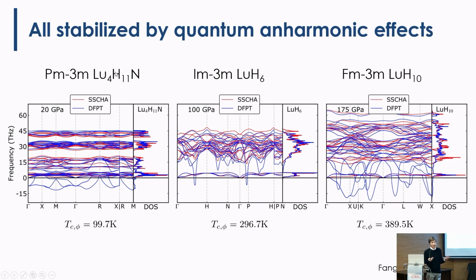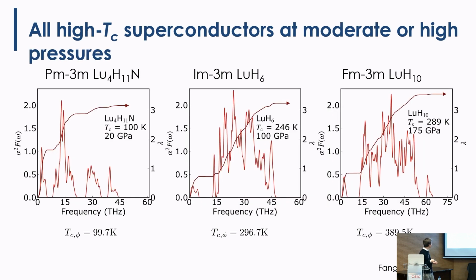So we can have an error in the calculations, okay? 20 GPa is not that much, okay, in this scale. So maybe this is dynamically stable also at lower pressures. And the TC that we calculated is 100 Kelvin, so it's not that bad here, okay? So I was a bit curious about this. So maybe there is here something.